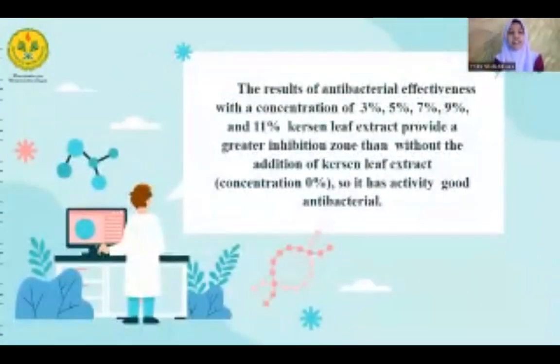The left table is the result of the antibacterial test of soap against Staphylococcus aureus bacteria, and the right table is the result of the antibacterial test of soap against Escherichia coli bacteria. The result of the antibacterial effectiveness test of liquid soap of Kersen leaf ethanol extract at a concentration of 5% is categorized as optimum against Staphylococcus aureus bacteria, and at a concentration of 3% categorized as optimal against Escherichia coli bacteria. From the result of this study, the antibacterial effectiveness with concentrations of 3%, 5%, 7%, 9%, and 11% Kersen leaf extract produced a greater inhibition zone than without the addition of Kersen leaf extract, or concentration 0%. So it has good antibacterial activity.